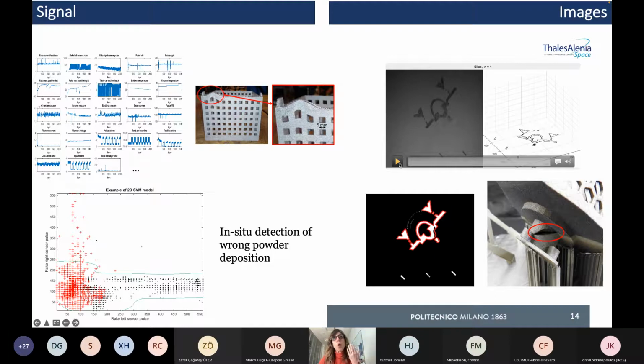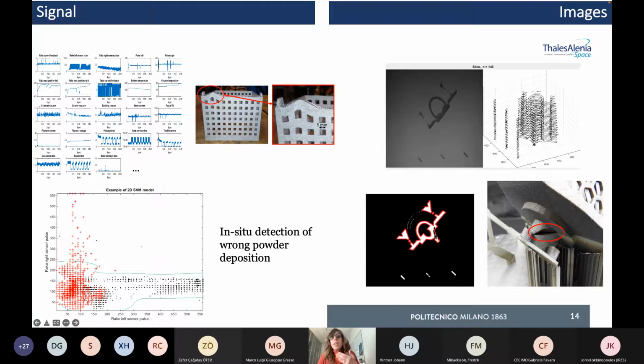We can even take the picture of the sliced part as soon as I've been printing the part layer-wise. So while I'm in the machine and I'm printing the part, this is a direction we do believe is really, really relevant, because it's some sort of geometrical inspection that is done in real time, layer by layer. At each layer, you can reconstruct what you have been printing. You can compare what you have been printing with the nominal shape you should have printed at that specific layer. The red border is the nominal, while the white is the one that you have printed at one specific layer. And in this real case study, we saw that the defect that at the end was resulting was almost easily detectable in situ and in line just by playing with this image of what you were printing.